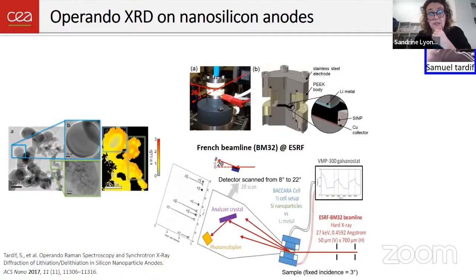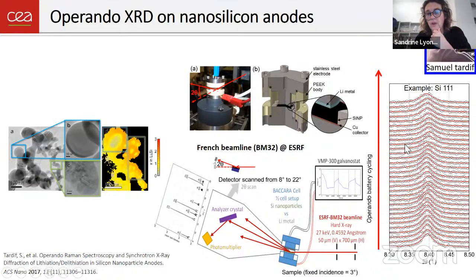What we did is we built a cell that enabled us to perform the operando measurements in good electrochemical conditions. And we went to BM32 beamline, which is a French beamline at ESRF, and performed a kind of standard, let's say, XRD experiment where we look at Bragg peaks coming from the crystalline silicon and how they evolve during the charge and discharge of this battery.